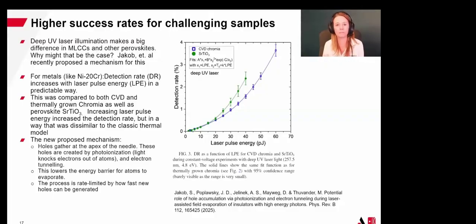And the new proposed mechanism suggests that holes might be generated and gather at the apex of your needle. These holes would be created by that photoionization mechanism, and that would lower the activation energy for atoms to evaporate. And this process is really rate limited by how fast holes could be generated from the deep UV laser pulse.